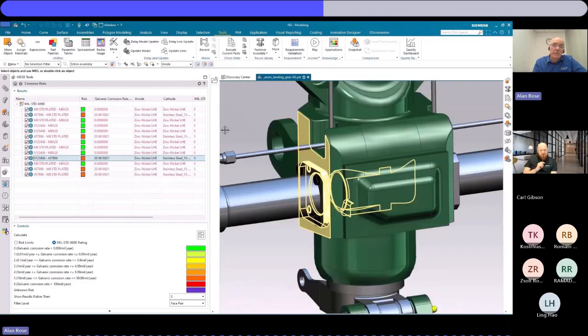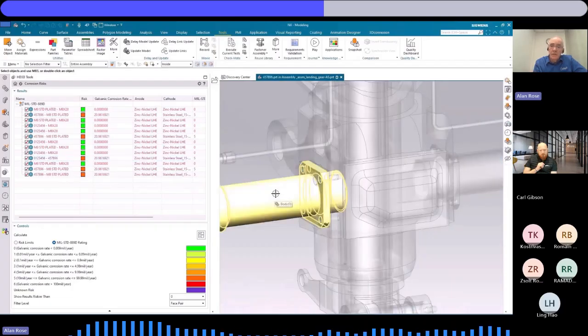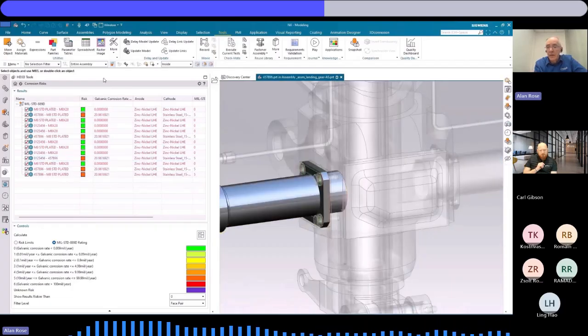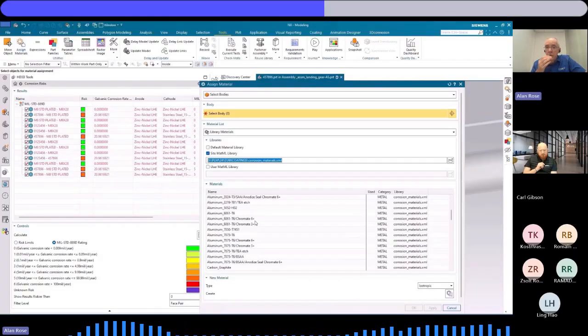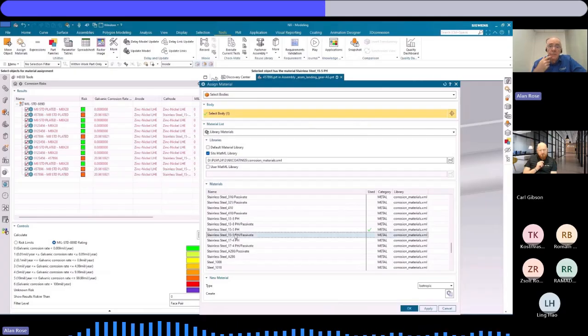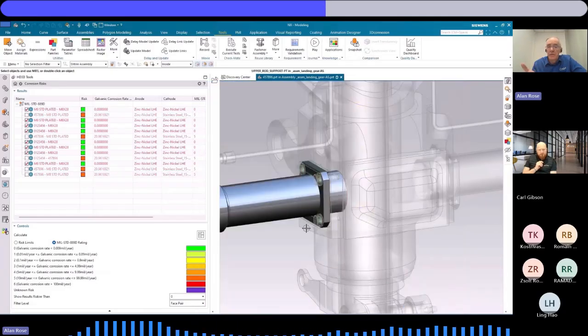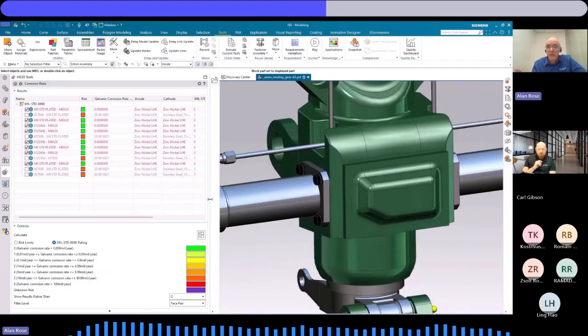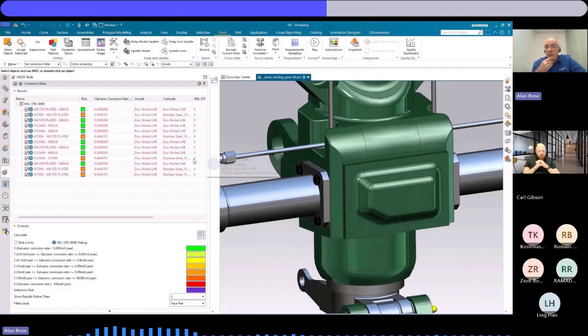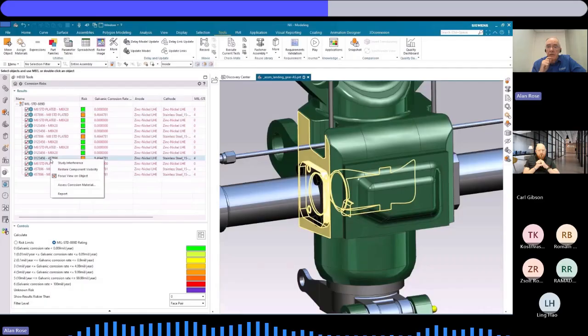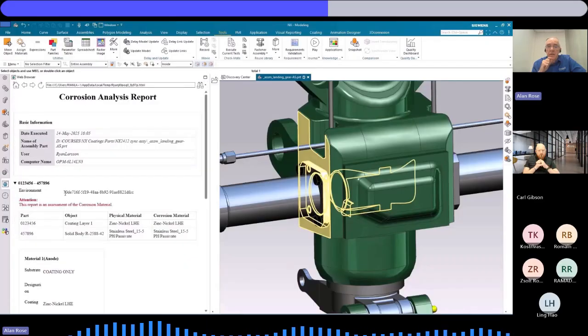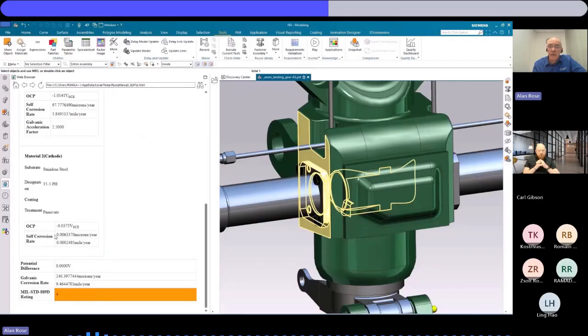So it's great because then you can home in here on the piece that may be causing you issues. You could just do a change of coating on the fly. We're looking here at the difference between 15-5 PH and whether we passivate it or not, and you can halve the corrosion rate by just passivating it. Well, you can halve the consumption of the surrounding zinc nickel by passivating that stainless steel piece. Okay.